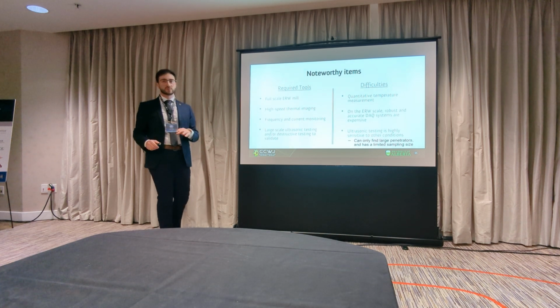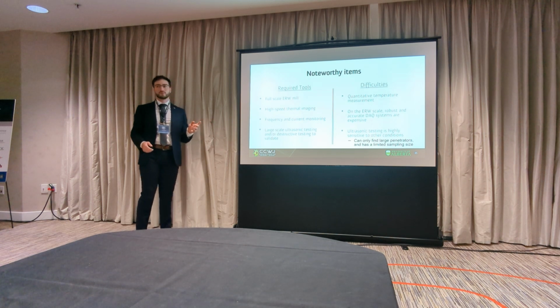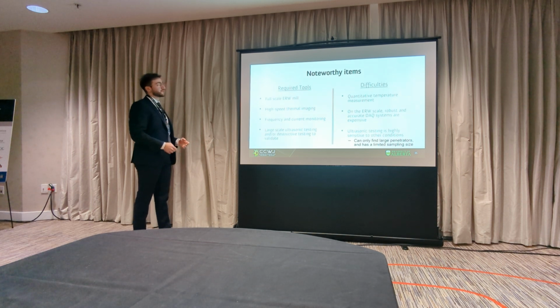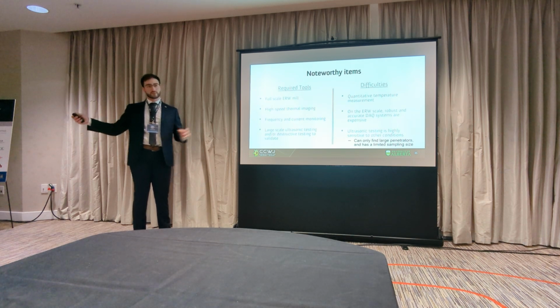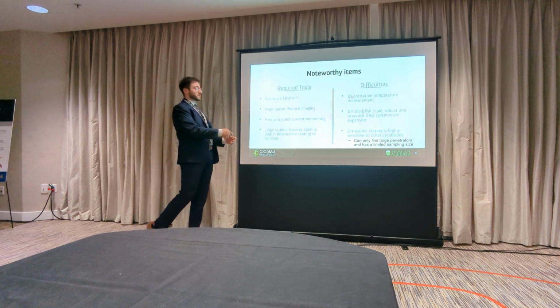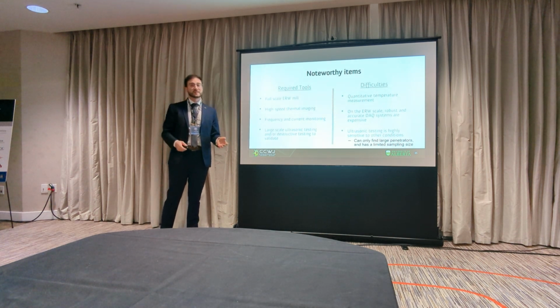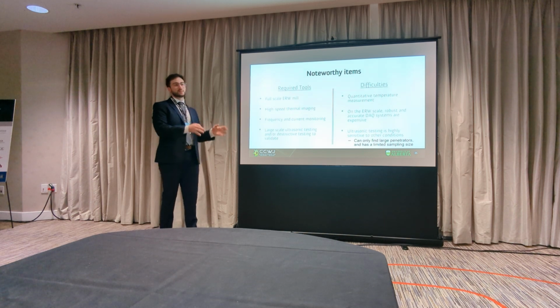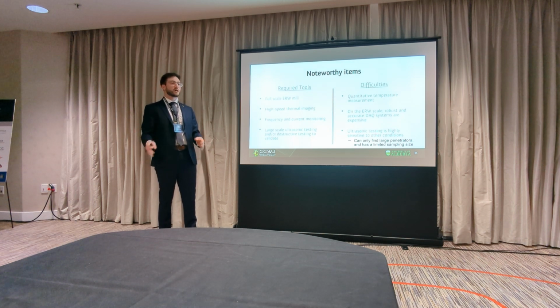So some noteworthy items to do this testing. You need a full-scale ERW mill. You also need high-speed thermal imaging to actually validate the temperatures that we can predict with the heat model. Also, frequency and current monitoring would be beneficial because we want to link unstable process predictions by temperature with the unstable process conditions by frequency monitoring. Large-scale ultrasonic testing and/or destructive testing is necessary because we are predicting penetrator formation by process instability. And so we'll say, okay, at this point, this process was unstable. We think there's a penetrator there. How do we tell? We have to crack it open. So that's why we need the destructive testing.